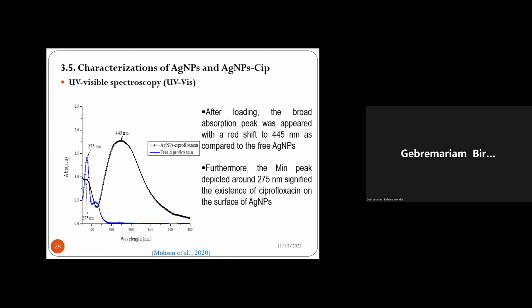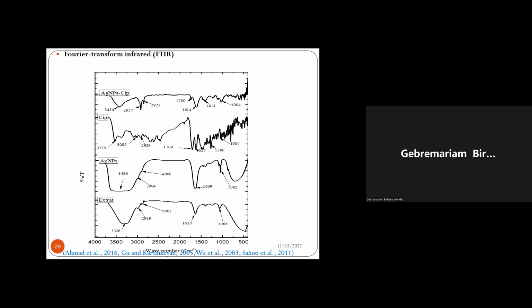So the loaded nanoparticles, to confirm the loading of the ciprofloxacin on silver nanoparticles, further analysis was done, and as we see, there is a big difference in lambda max, or the spectrum, of silver nanoparticles and ciprofloxacin-loaded silver nanoparticles. So this confirmed the successful loading of ciprofloxacin on silver nanoparticles, and even the infrared spectrum also confirmed the successful loading of the ciprofloxacin to the synthesized nanoparticles.